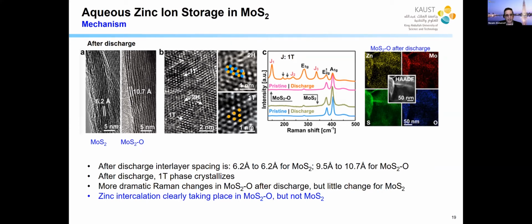Another interesting thing happened actually during the intercalation of zinc. The hexagonal molysulfide transformed to 1T, which is a different form of molysulfide. And so that is a phase transition caused by the zinc intercalation. It turns out we're using this for other applications because this was not known before. People did this with lithium, but this was the first time we could see that by electrochemically intercalating zinc in molysulfide, you can do a phase transformation. The Raman here shows the molysulfide, this is the blue and the yellow, not changing at all after zinc intercalation because not much intercalates, but substantial changes in the pink are taking place because of the phase transformation.